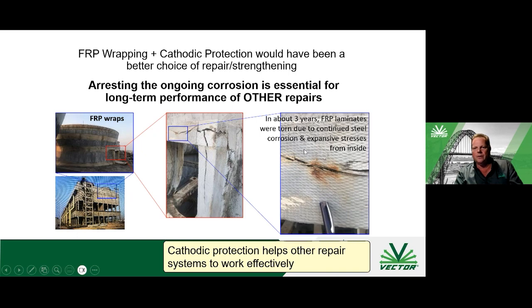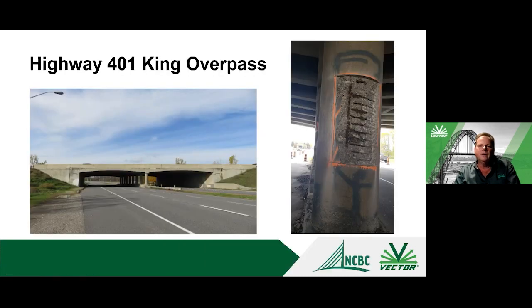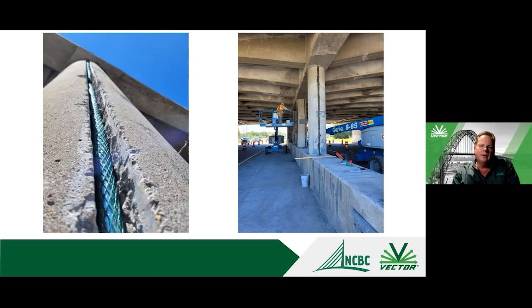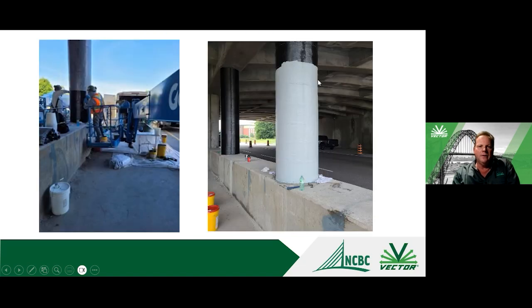Here's an example of an FRP that's been applied onto a corroding structure, and you see some failure of the FRP and rust staining. So this is just one example, where you see some chloride-induced corrosion related spalling, and these needed to be strengthened. This is one technique where they chipped a pocket vertically on a couple sections of a column and connected distributed galvanic anodes into the slot. Those slots were grouted back, and then the strengthening was placed on the outside. So you have a strengthened structure with a galvanic protection system underneath of it.